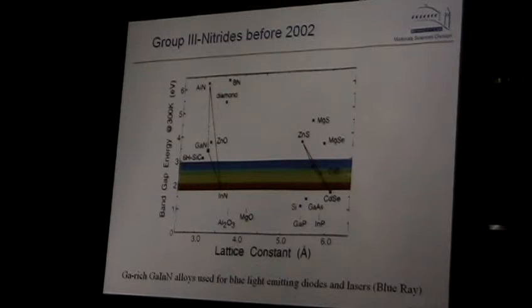What happened is that everybody thought its gap was around 2 electron volts. However, it was not certain because nobody could get any photoluminescence from the material. And gallium nitride, or nitrides, are very successful. If you have a so-called Blu-ray player, then this is something which is made of material around gallium nitride. This is the blue laser.